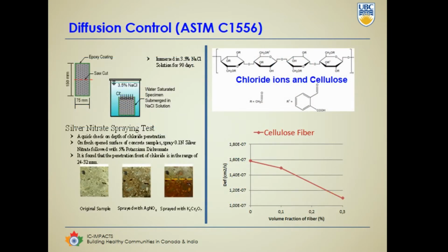Cellulose is also a binding material. It binds chlorides, the ones that come through your de-icing salts. And here we have a very clear indication that your actual diffusion coefficients are less through a cellulose modified system. And finally, the proof of the pudding is always in corrosion control, because that's what the first slide I showed you was about: our structures are corroding. All the rebar in our structures is corroding.